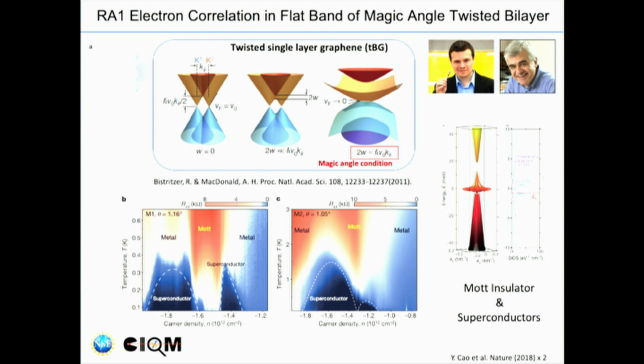But what was even weirder is that if you, quote, dope it a bit by changing the density to be not perfectly filled, but some holes or electrons in there, it becomes a superconductor. And the resistance goes exactly to 0. And carbon, previously in a crystal, doesn't superconduct, period. And all of a sudden, you made carbon a superconductor by rearranging the atoms. That is something that's generated, what, more than 50 theory papers, none of which actually explains why it occurs.